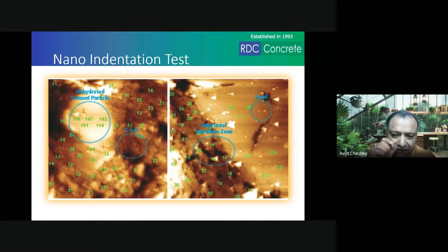So it's a needle with a very small diameter. Actually, it's triangular in shape. And what they do is they prick this at different points inside the concrete and measure the strength of those points. If you see in the unhydrated cement particle, when they pricked, the numbers that they got are 105, 107, 102, and so on. Whereas inside the CSH paste, they were getting numbers of 17, 13, 23, almost 7 to 10 times less than the strength in the unhydrated cement particle.